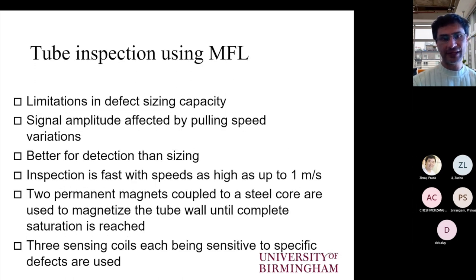So, as I said earlier, MFL has restrictions in defect sizing capability. It is a more qualitative and at best semi-quantitative method rather than quantitative. The signal amplitude is affected by the pulling speed, so we have to ensure that there are no variations when we do the inspection. We have to do the inspection at consistent speed, and of course that speed has to be somewhat limited. It is a relatively fast method, but obviously we cannot move the probe too fast, because that will increase the eddy-current effect and will change the sensitivity level of the inspection that we are doing. It is generally a better method for detecting rather than sizing.